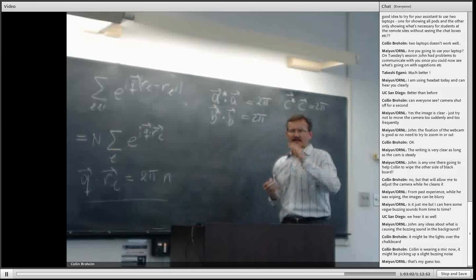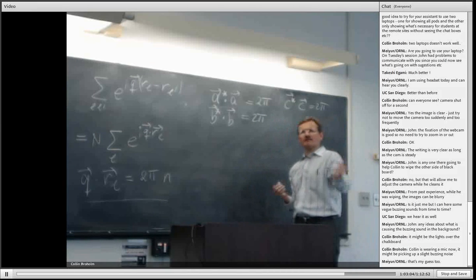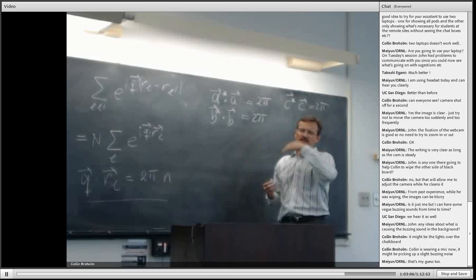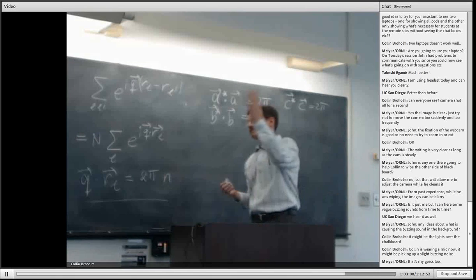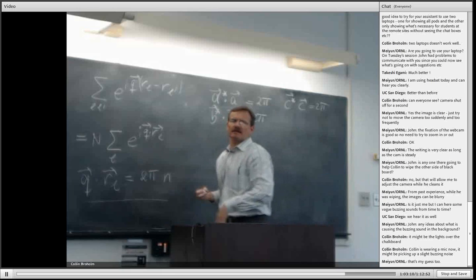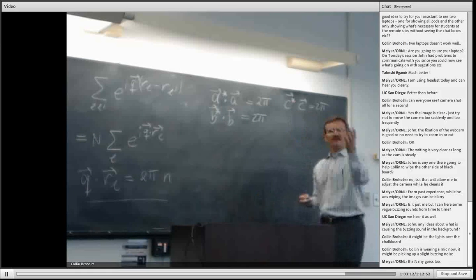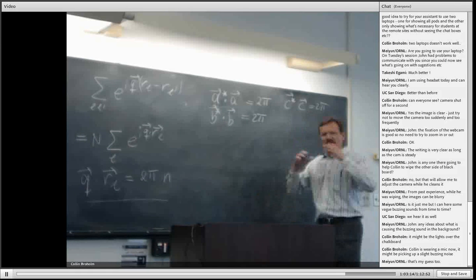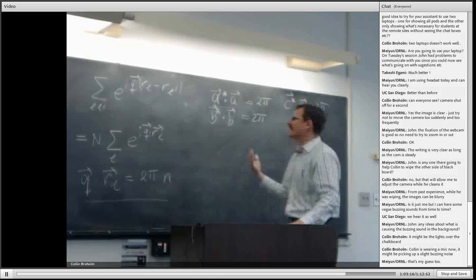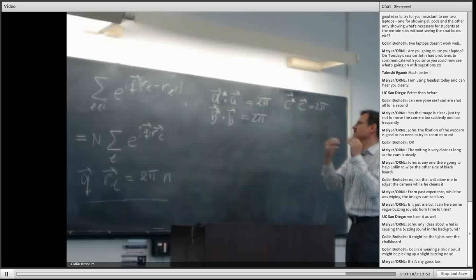So as a reciprocal to the cubic lattice, we find once again a cubic lattice. Reciprocal to the hexagonal lattice, we find once again a hexagonal lattice. Reciprocal to FCC, we find BCC, etc. So there's a direct connection between the real space lattice and the reciprocal space lattice.